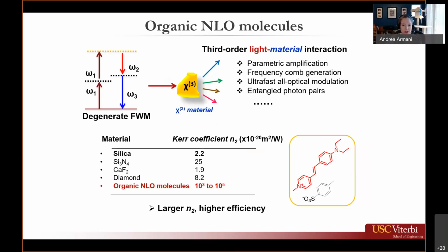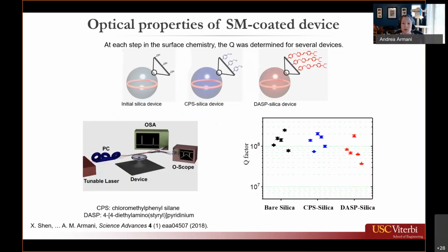And just for some comparisons, silica, silicon nitride, calcium fluoride, and diamond are all on the order of 10 to the negative 20 meters squared per watt in terms of their Kerr coefficient. In comparison, some of the high performing organic nonlinear optical materials are in the 10 to the 3 times 10 to the 5 times 10 to the negative 20 meters squared per watt. So they're significantly higher Kerr coefficients, which gives you a little bit of a buffer when you start developing a device, right? Even if you degrade their performance, you still might have a higher performing device.